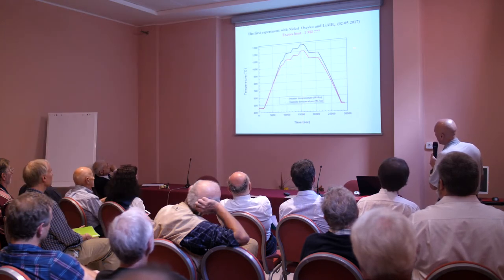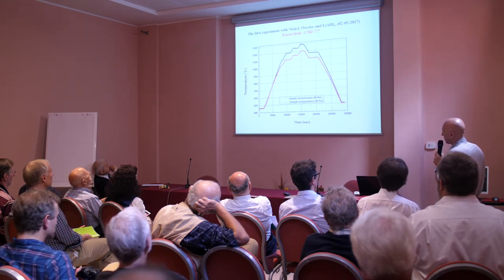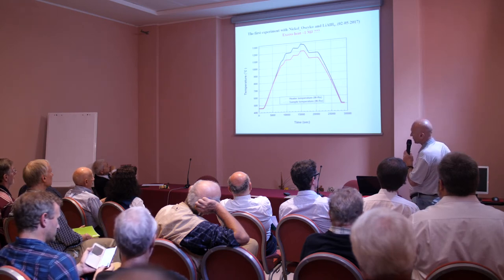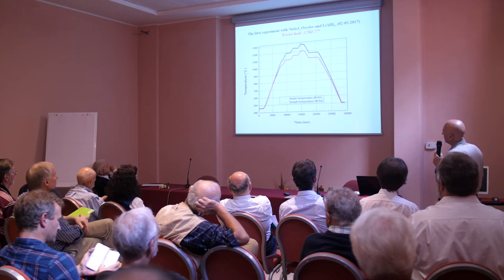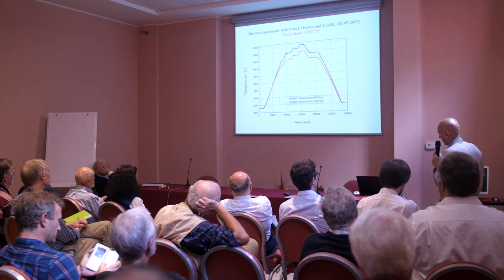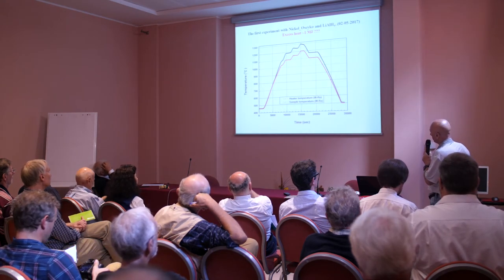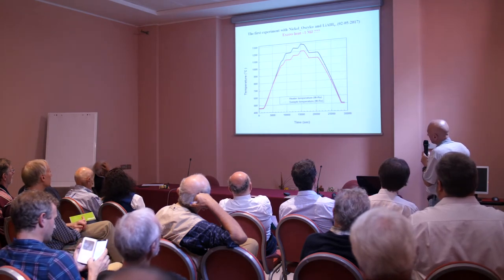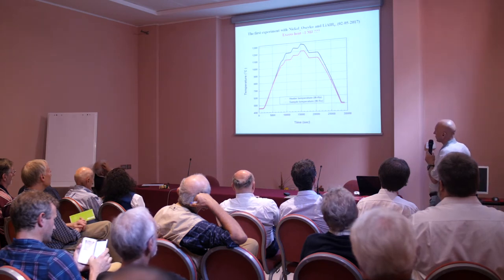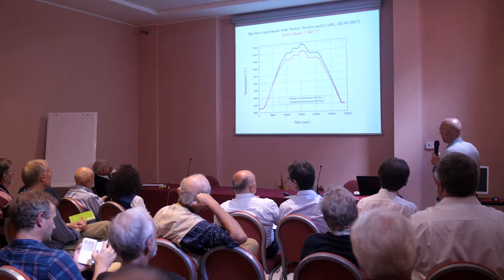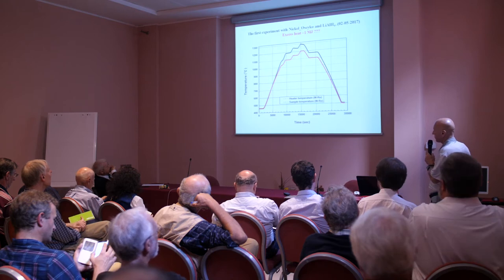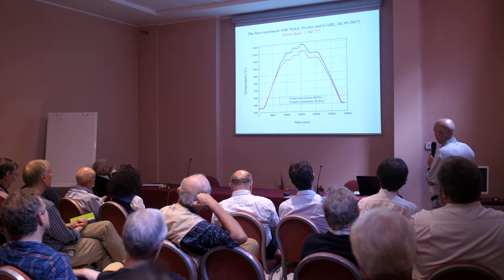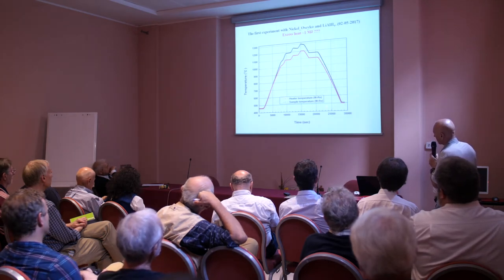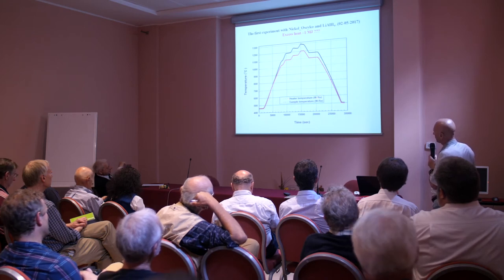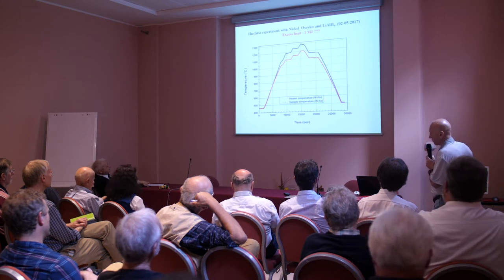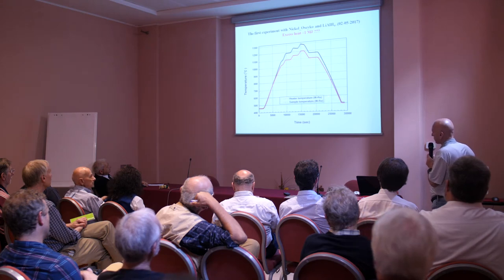And when we stabilized the input power, it lasted approximately 4 days. And if this temperature difference were produced by excess heat, then it would be of the order of 1 megajoule, which was probably 2 orders of magnitude larger than all the energy produced by burning of the present hydrogen. But I forgot to mention that in this setup we used a different type of thermocouple, tungsten rhenium, and we calibrated it before in pure hydrogen, and it is known to be very thermal resistant.